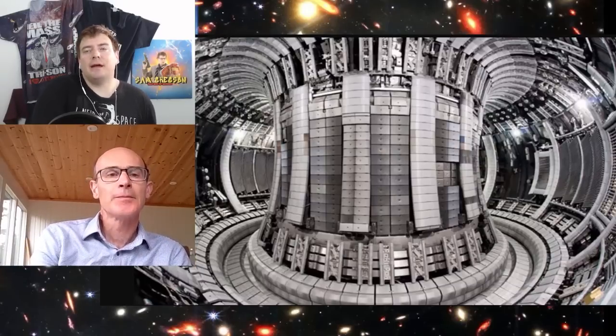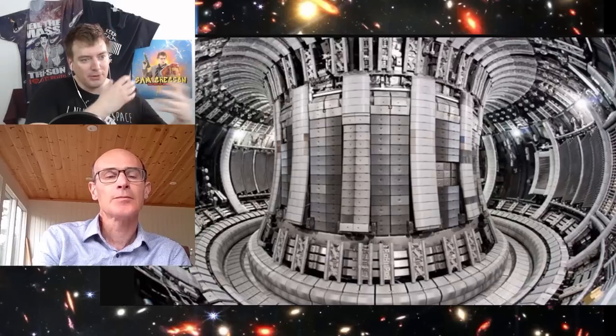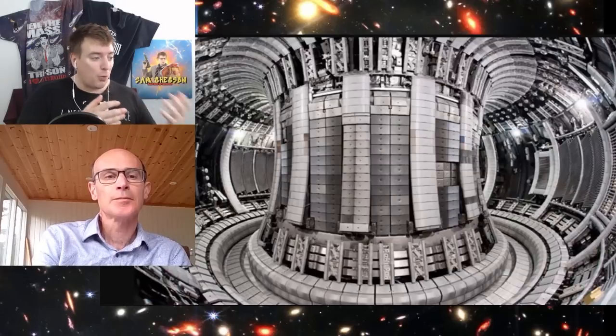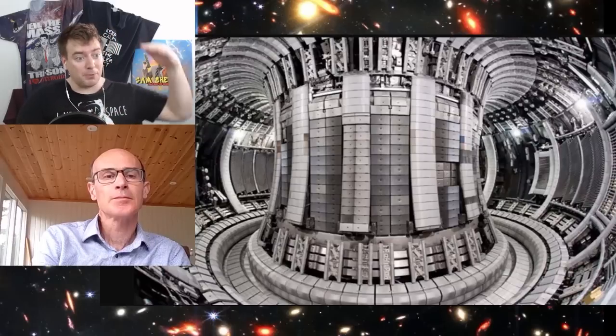This was something that I see for particle colliders going forward, particularly particle colliders that have decay products spray against the wall. So, for example, people have talked about a potential muon collider where the muons are decaying and hitting the wall. That puts heat into the superconductor, and the worry, therefore, is that they can quench, and then they stop the particles going around. But if you could produce something that has a very high quench point, close to room temperature or even higher, then obviously those thermal loads become not so much of a problem. So people have talked about applications potentially for fusion reactors, potentially for future particle colliders, things like this.